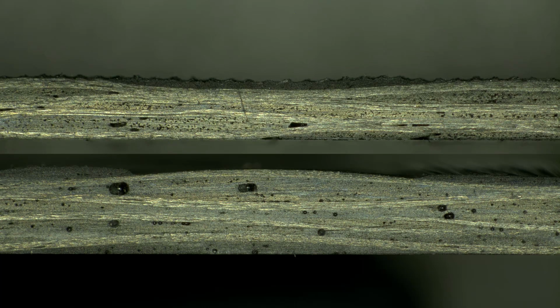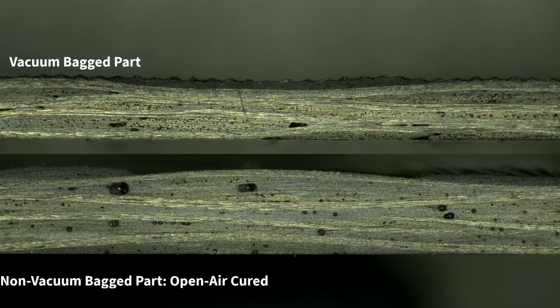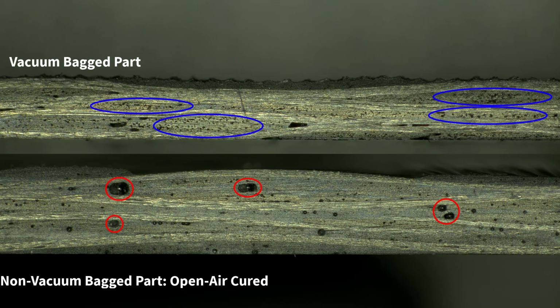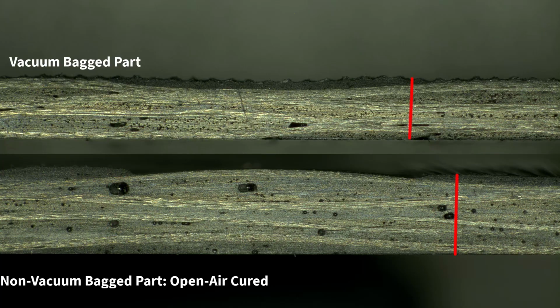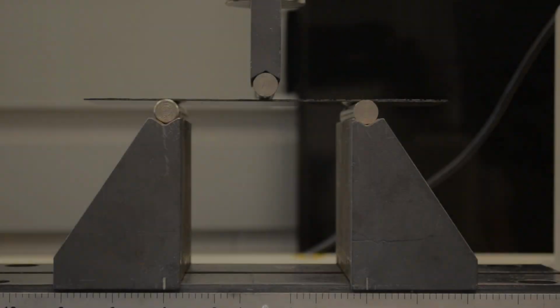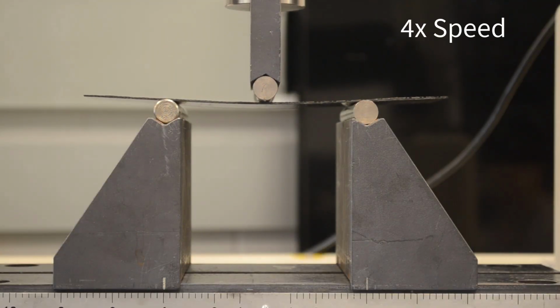After sectioning the samples, we can observe the internal void content. The vacuum-bagged samples had consistently fewer large internal voids, but did have considerable amounts of smaller porosity. The voids tend to be oblong instead of spherical, as the fiber bed has been compacted by the consolidation pressure of the vacuum bag. It is also apparent that the thickness of the vacuum-bagged part is smaller than the open-air cured samples.